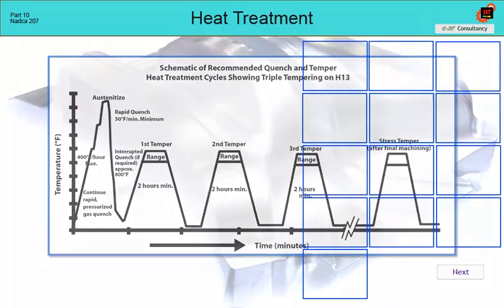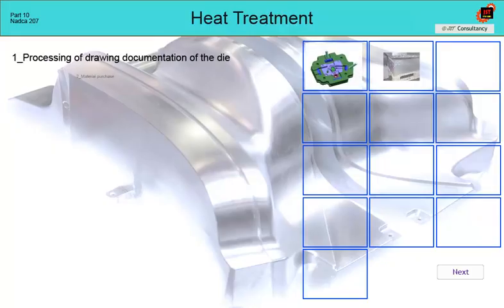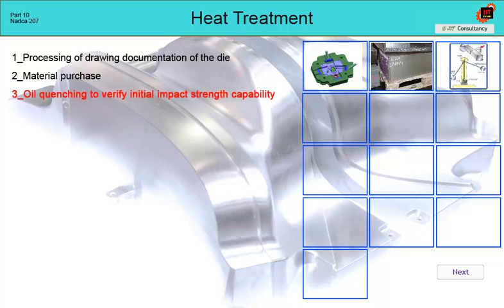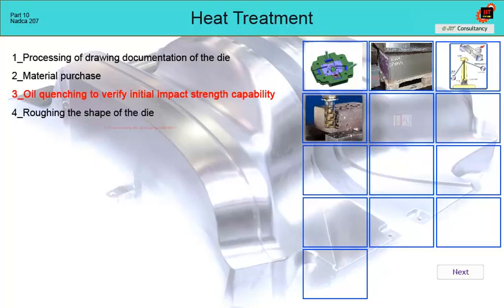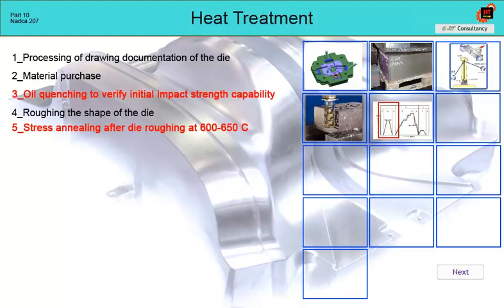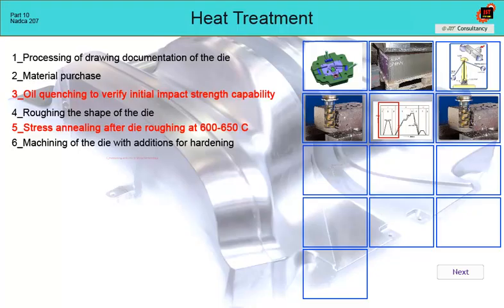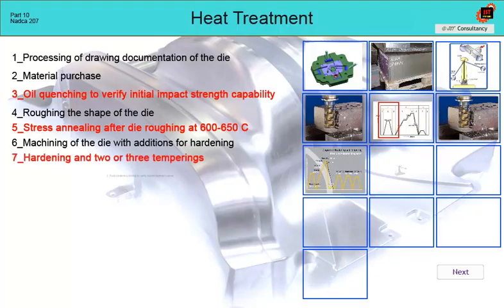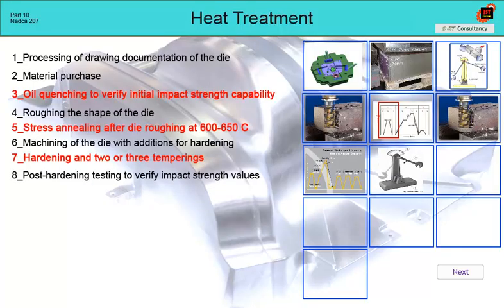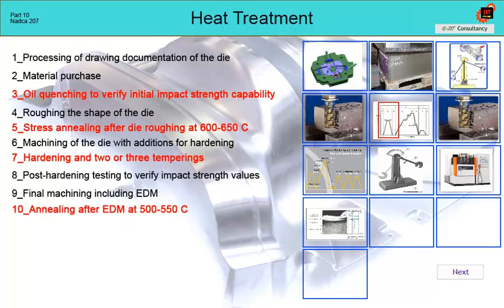The usual procedure is as follows: drawing documentation of the insert, purchase of material, input testing of material with ideal oil quenching to verify steel material capability, roughing the shape, annealing to remove stress at a temperature of 600 to 650 Celsius, machining of the insert with additions for hardening, hardening and 2 or 3 temperings, material testing to verify impact strength after hardening, final machining of the insert including EDM, annealing after EDM at 500 to 550 Celsius, post-oxidation of the die surface to improve run-in properties.